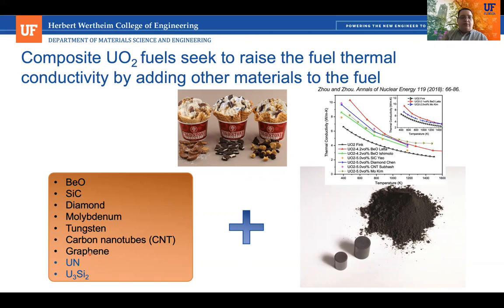Now, all these materials that are colored in black here are non-fissile materials. And so for all the volume fraction that we add, we're actually lowering the uranium density, and so we're lowering the amount of heat being generated. So we don't want that volume fraction to be too large. The exception to that are these two that I've shown here in blue, uranium nitride and uranium silicide, which are fuel materials. In fact, they have a higher uranium density than UO2. And so they not only raise the thermal conductivity, they raise the fuel density as well.